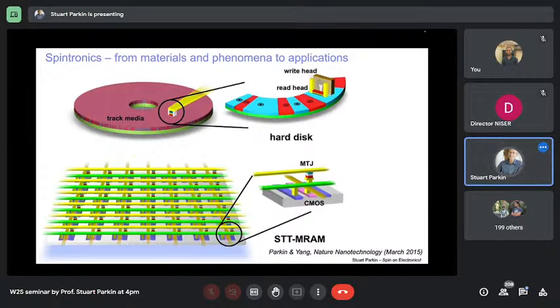Now, it turns out it's much more complicated than that simple cartoon, because we actually design the magnetic moment of one layer to be orthogonal to the magnetic moment of what we call the reference layer. And then, as in this cartoon, when the spin valve device is moved over the surface of a magnetic film in a magnetic disk drive, in which the data is encoded, you can see here there are blue and red domains where the magnetization points up and down, and the boundaries between these regions give rise to some tiny magnetic fringing fields, and these are then detected by the spin valve, and the maximal sensitivity is when the two magnetic layers in the spin valve have their moments orthogonal to one another. So I'm again not going to say much more about spin valves.